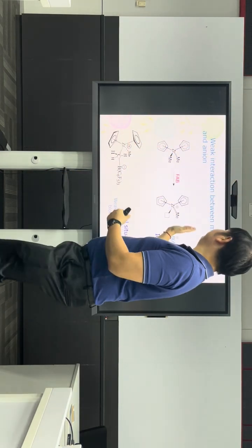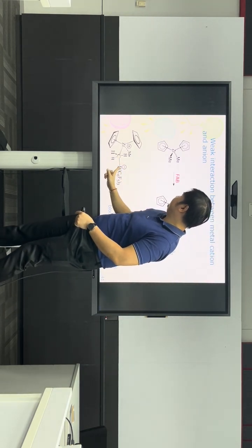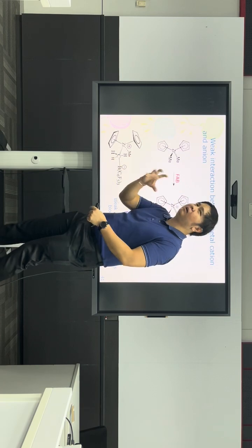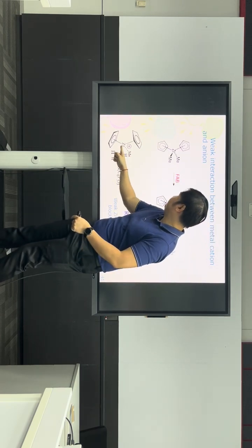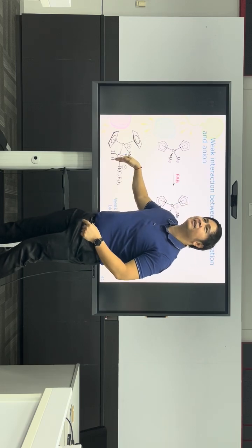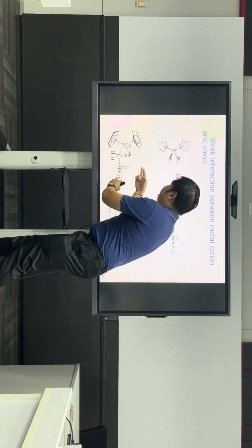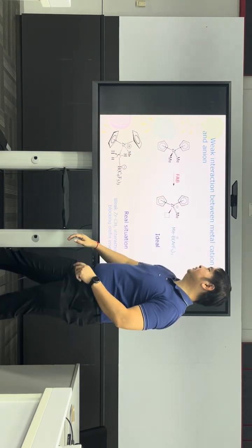Because the methyl is small, carbon can bridge between the metal and the boron. It doesn't go anywhere, it still stays around. But if an olefin comes in, this can be replaced with ethylene to do the coordination.